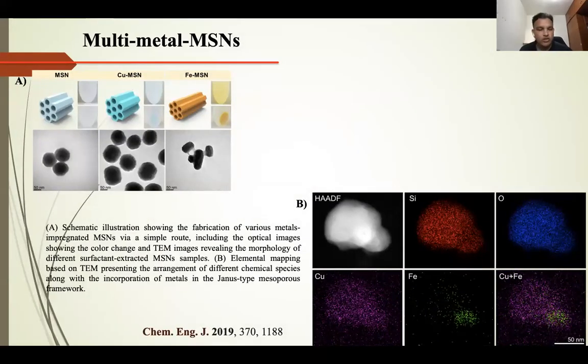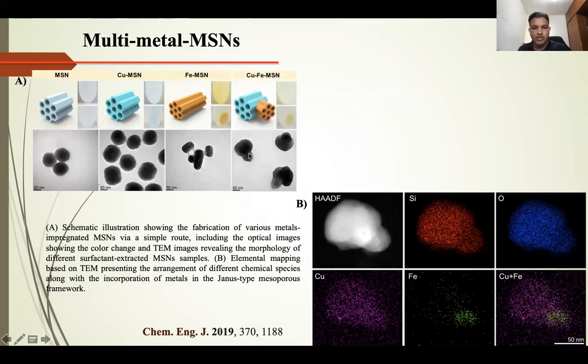So by the craziness of this metal incorporation into the silica framework, I got an idea: why don't we use multiple metals? Like, what is the situation of not just putting one, but also two? So I tried to use copper as well as iron inside. Then the crazy thing happened: we got a Janus type, like an extension, where two similarly charged metals try to repel each other, and then try to extend the framework into special shapes.